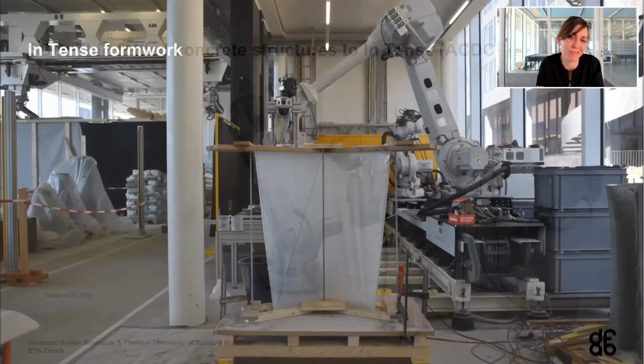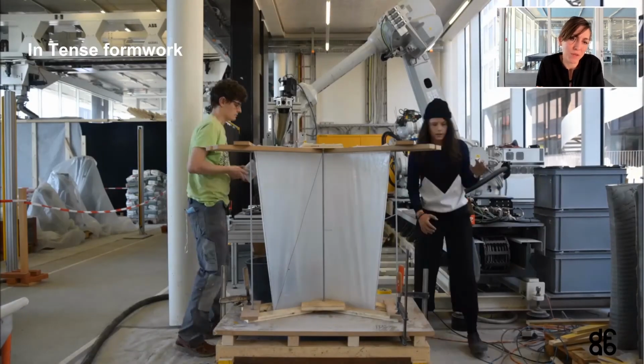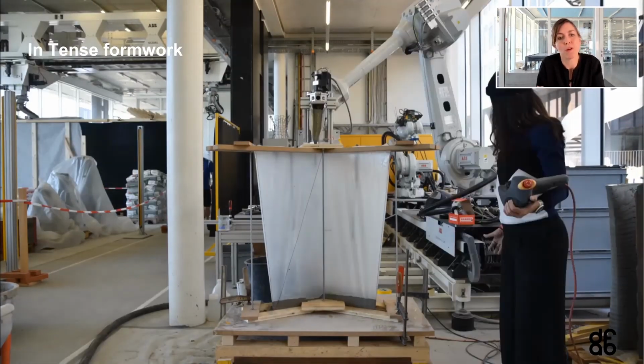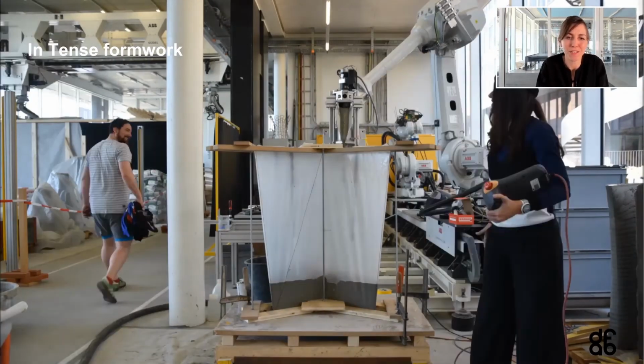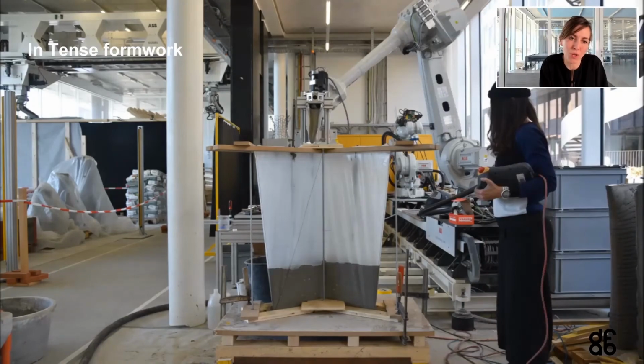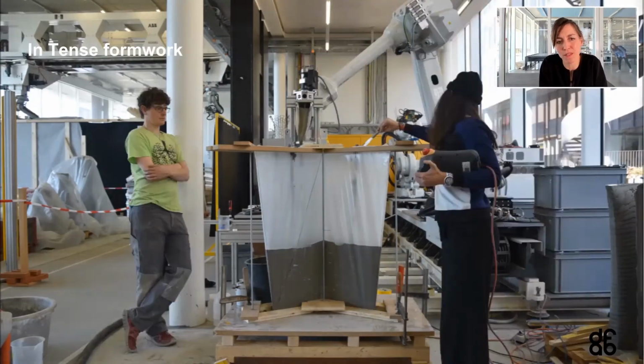Okay, so Anna went from thin folded concrete structures to intense formworks, which she also calls ACDC, additive controlled digital casting. So instead of moving a slip form vertically, the goal was now to use thin materials that were weakly supported and then filled with set-on-demand materials that used a commercial acceleration system in combination with superplasticizers. And here you see one of the very first successful prototypes, which were actually very fast done. She filled up this more than 1 meter tall formwork in less than 25 minutes.